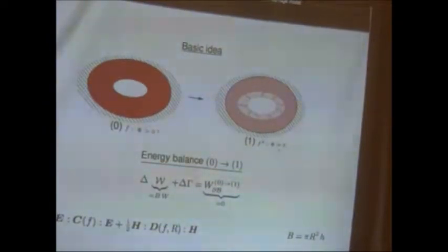You put this volume element under stress, so to say, by means of displacement or prescribed displacements on the boundary. The volume element suffers and says, okay, I need relaxation, and we say, okay, but we won't relax on the boundary conditions. The only thing you can do for relaxation is let the void grow. And we envisage the following mechanism for this void growth.